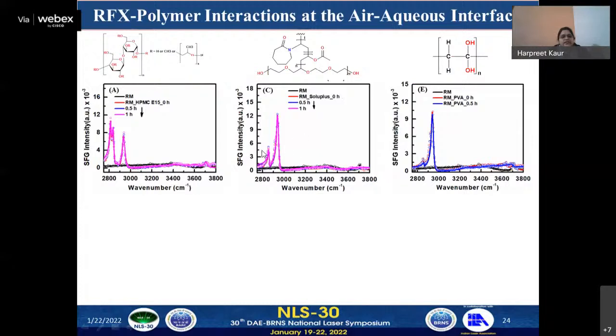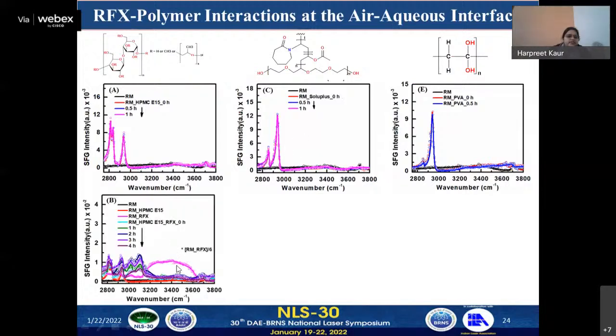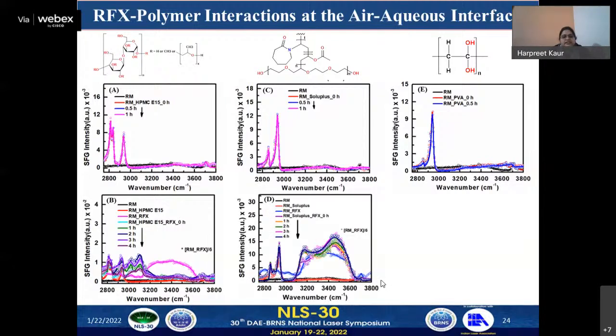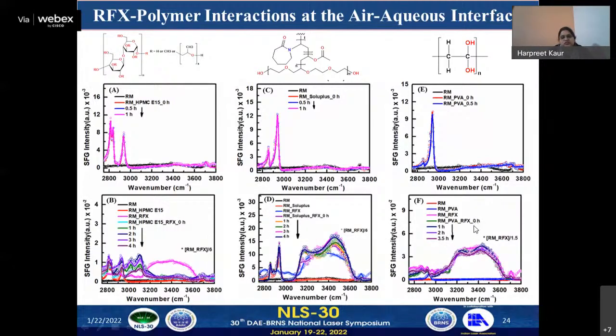But on introduction of the drug to the system, in this HPMC polymer, we have found that this enhanced intensity is actually decreased during interaction of this polymer with the drug, and the signatures in the CH stretching region are also dominating, which confirms that there are very prominent interactions between this drug and polymer. While the reverse case is found in the case of Soluplus and PVA.